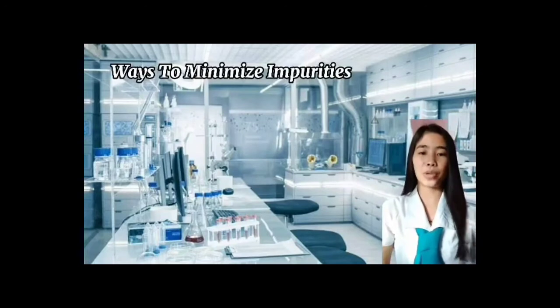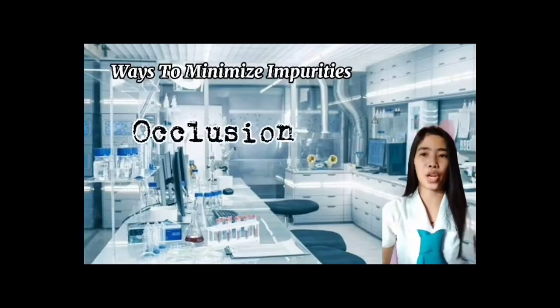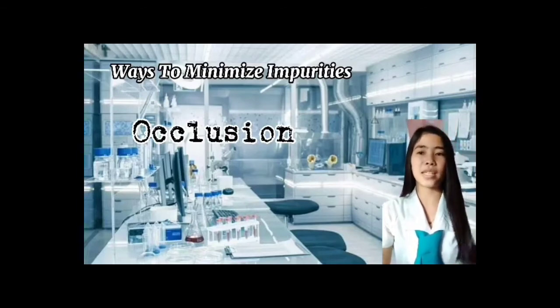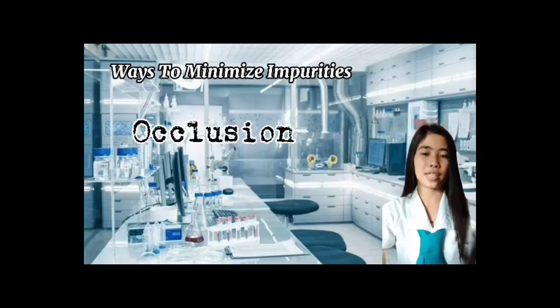The second type of impurity is what we call occlusion, which occurs when an interfering ion is trapped within the growing precipitate. We can minimize occlusion by maintaining the precipitate in equilibrium with its supernatant solution for an extended time.